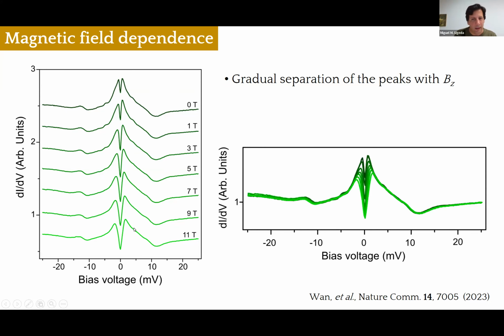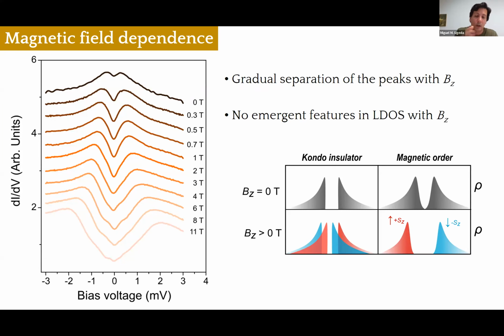Here I show you all the curves overlaid so that you can see that there are no new features except for this gradual separation. In this set, which was taken with much higher resolution, you can see that the peaks behave similarly, and there are no new features showing up for large magnetic fields. So there are no emergent features in the density of states with the magnetic field, and therefore we are in a good position to rule out the possibility that we are looking at a Kondo insulator regime, right? Because we should observe a splitting of these peaks if it was a Kondo insulator system. So the only compatible possibility is the magnetic order.